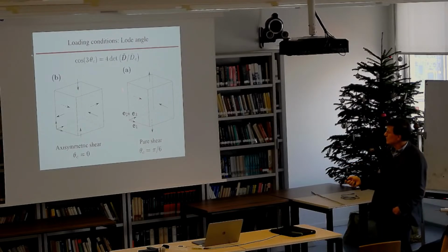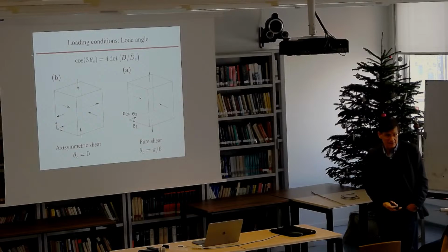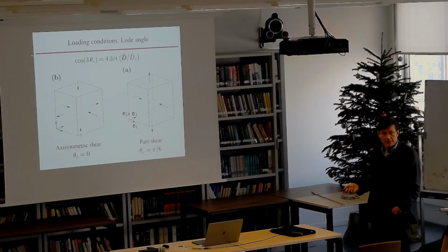And for that reason, we consider two cases: axisymmetric, so you pull in this direction and you compress in the transverse plane, or pure shear, where you pull in this direction, you compress in this direction, and you hold it fixed in the other direction. These are two different ways of loading the material that for linear isotropic suspension would give you exactly the same result. But in the nonlinear context, they may not.